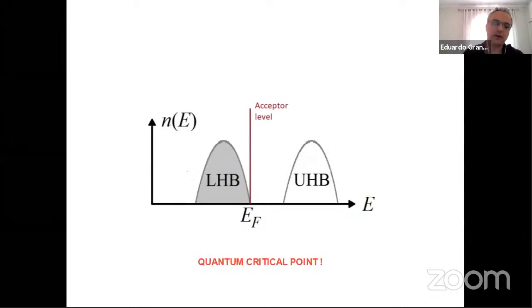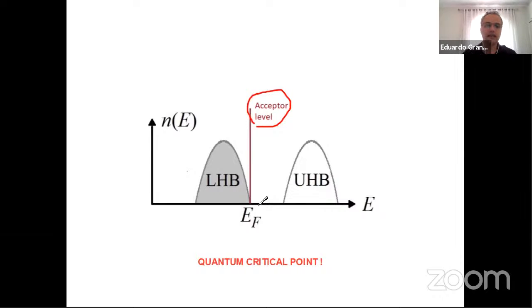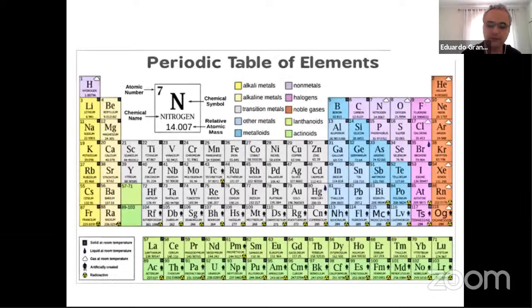But if you are smart and lucky at the same time, you may have an acceptor level that matches exactly the Fermi energy. And that gives a behavior which is neither metallic nor insulating, it is exactly at the quantum critical point. That's the point where you may have a quantum phase transition. And with the little time I have left, I want to convince you that's what we have in the material that we studied.